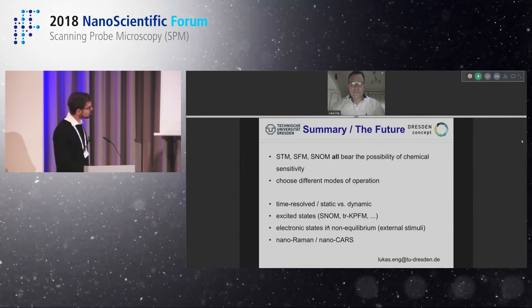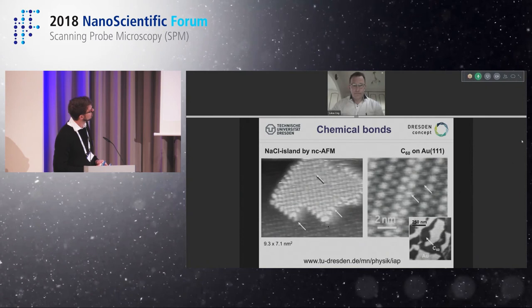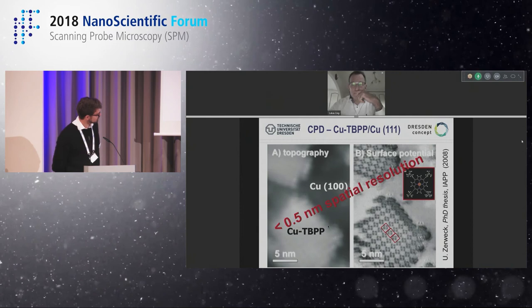You showed this slide from the PhD thesis from Mr. Zerweck, the copper surface, where you showed the topography and also the surface potential. If we could go back to the slide. This one. Yes, right. So we see the topography is quite blurred in comparison to the surface potential. So first question would be, was this measured in ambient conditions or was it low temperature, ultra high vacuum? That was ambient, but it was actually under ultra high vacuum. Okay. So the temperature was room temperature, but ultra high vacuum.